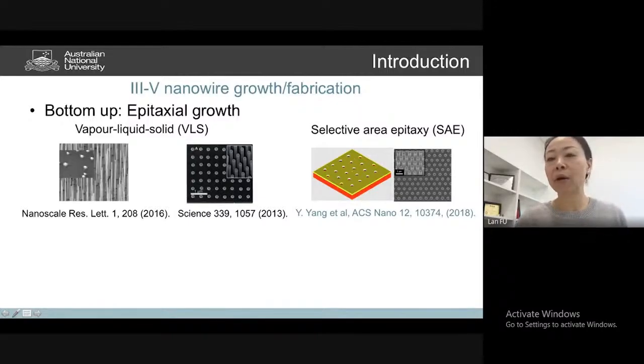On the other hand, we can also use another, more template-based technique, where we don't have to use the metal nanoparticle, because a metal nanoparticle could sometimes introduce contamination into your system, which is not favorable for device applications. Also, you have some limitations in terms of dopant incorporation, or you have problems growing larger-size nanowires. So there are some issues and limitations there. An alternative way of making them is to cover your semiconductor substrate with a thin layer of oxide, such as silicon dioxide, and then use nanolithography to define the positions of the nanowires. Then you use dry etching or chemical etching to open up holes there, and then you put this into the MOCVD reactor to grow nanowires.